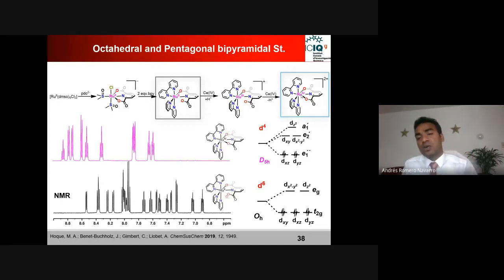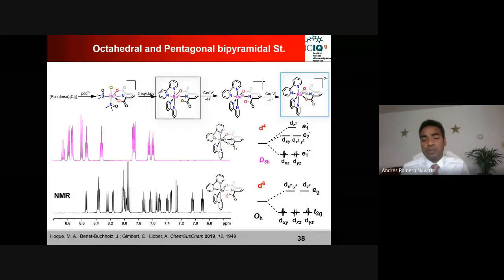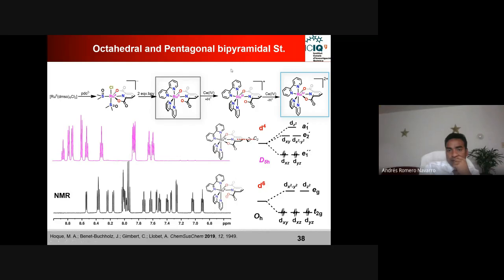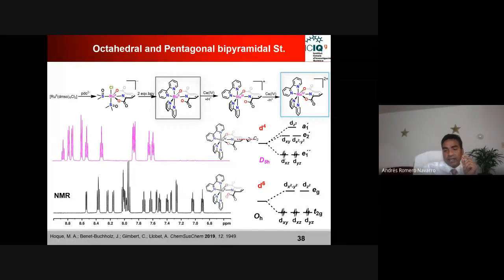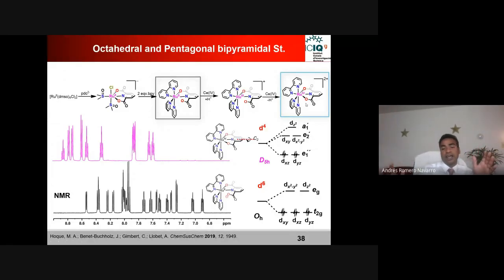If you look at this ruthenium-4 compound, it has 7 coordination. So basically it is forming this pentagonal bipyramidal geometry. Normally not all molecules can show this 7 coordination property. The reason this molecule is showing this 7 coordination is that, as I mentioned, it is forming this pentagonal bipyramidal geometry. And if we do this orbital splitting, now we don't have any unpaired electron, and that is why this is showing again the diamagnetic NMR. But you see that visually, all this ligand environment and everything for this ruthenium-2 and ruthenium-4 are exactly the same. But due to the different oxidation state, their property has been drastically changed. And that is very obvious, because when we have this ruthenium-4, the NMR is significantly different than this ruthenium-2.